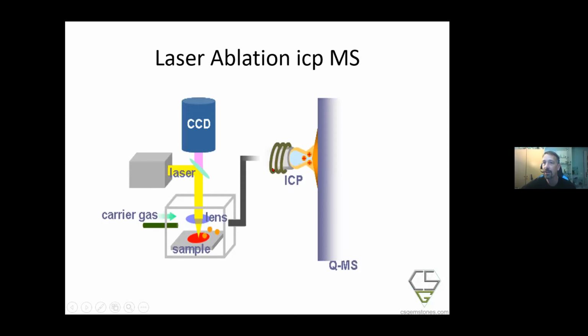However, I play a little bit more with laser ablation ICP-MS. So laser ablation is a system where you have a laser and you have a camera, you look at your sample and you shoot with a laser onto your sample. And then you make some nice explosions. These explosions are very, very tiny. We are damaging the stone, yes, that is true. But if you do it for a gemstone, for example on the girdle, you leave a spot of 10 to 50 micrometers diameter and a couple of micrometers deep. Without a loupe, you're not able to see them. And if you want to remove them, that's polished away within a couple of minutes.